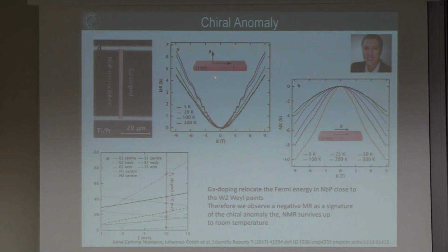But now we see if we have the magnetic field perpendicular to the current direction, we see a positive magnetoresistance effect, not as large as in the bulk material, but you'll see the size plays an important role in these materials, and we see a negative magnetoresistance if we have the magnetic field parallel.